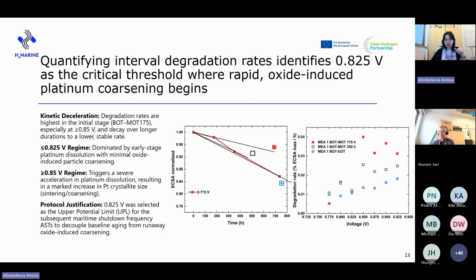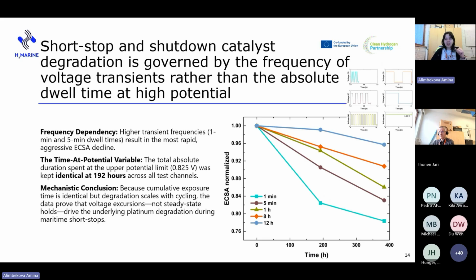Let's look now at the short stop and shutdown degradation. On this slide we have the electrochemical surface area versus the time for each dwell time: held for 1 minute, then the transient happens, held for 1 minute at the lower potential limit, and so on.